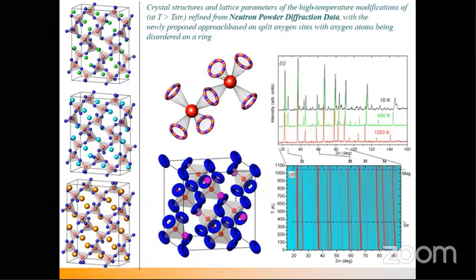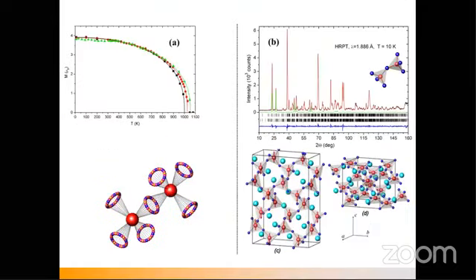Another important thing is that neutrons give us the additional feature of magnetic Bragg peaks, which were not seen in X-ray diffraction. So we get additional information on the magnetic nature of these materials, which show magnetic moments below 1000 Kelvin and above 1000 Kelvin. These are antiferromagnetically ordered materials, as I will show in the next slide, and they are magnetically ordered up to 1000 Kelvin. So very highly ordered antiferromagnets with a high Néel temperature of 1000 Kelvin. The magnetic moment remains stable up to 1000 Kelvin, and above that they become disordered or paramagnetic. So now these are the magnetic moment directions.